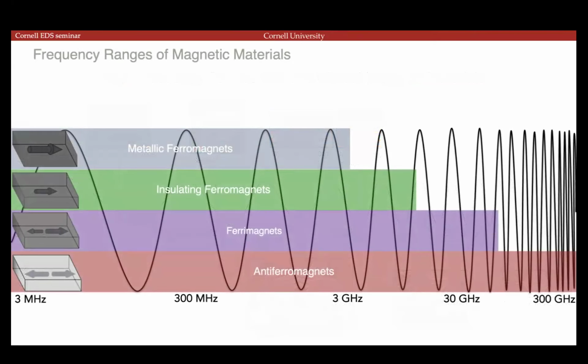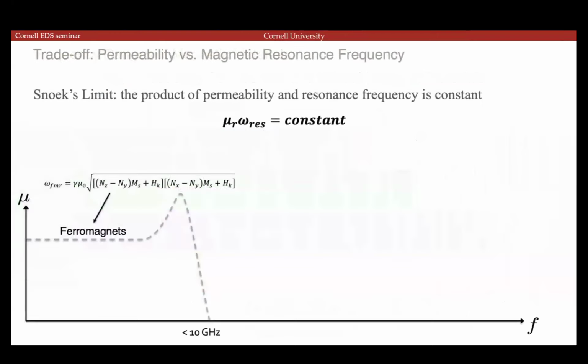And our goal is to keep the magnetic material in by, instead of using the typical metallic ferromagnets that have a resonance frequency of 3 gigahertz or below, or around the single digit gigahertz and below, we're switching to other types of materials. So ferrimagnets and antiferromagnets have higher resonance frequencies, and would therefore give us a larger bandwidth of operation that we can use.